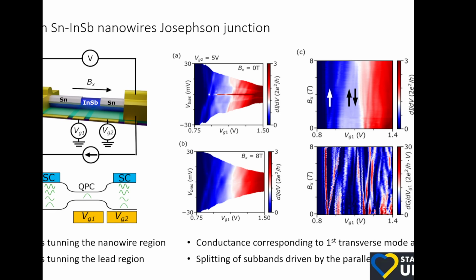Or there is so much back and forth and interference caused by trajectories going back and forth that it just obfuscates your ability to resolve. That's what happens in low mobility materials, where you cannot resolve the quantized modes. And that certainly happens in many of these samples as well. Only in a fraction can we find evidence of these plateaus.